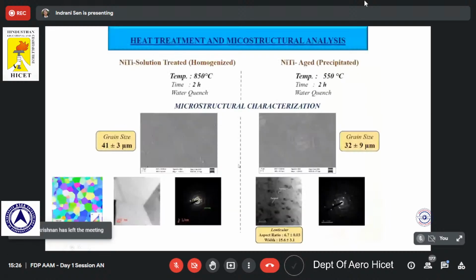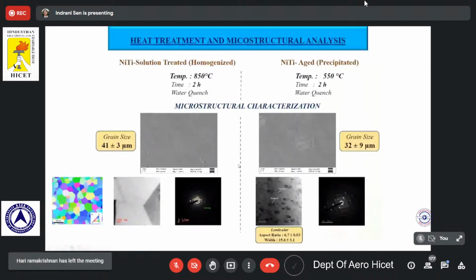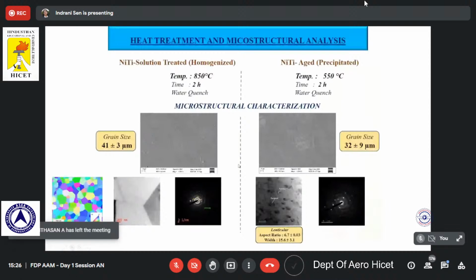Before that, we are coming back to the initial microstructural study. As I said, all the properties are finally related to their microstructure. So we always start from the microstructure itself. Now, in one case, we have a homogenized alloy, which shows the same picture that I have shown you earlier. So this shows a perfect austenite structure. And in the other case, where we have aged it at 550 degrees centigrade for 2 hours, we can see that there is the presence of precipitates.